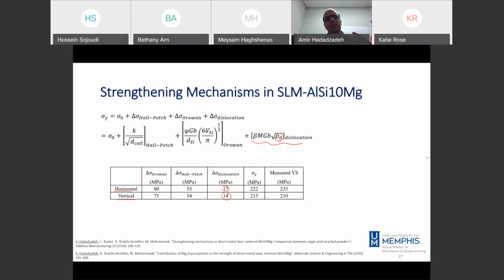However, there is an argument in the context of fatigue of AM materials. Many people believe that because of the defects in the AM materials, I mean, we still have some defects in the material by controlling all the process parameters, using good feedstock, controlling the environment, we still have the defects. And they believe that fatigue properties are controlled by the presence of defects rather than the microstructure. So the controlling mechanism, based on their idea,